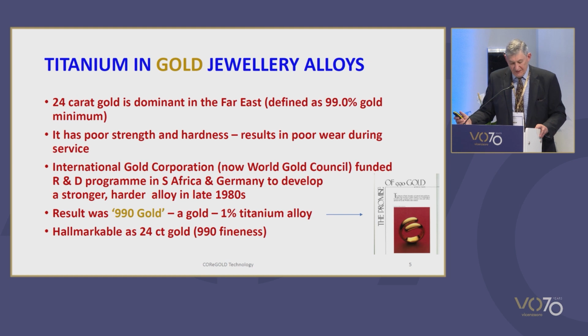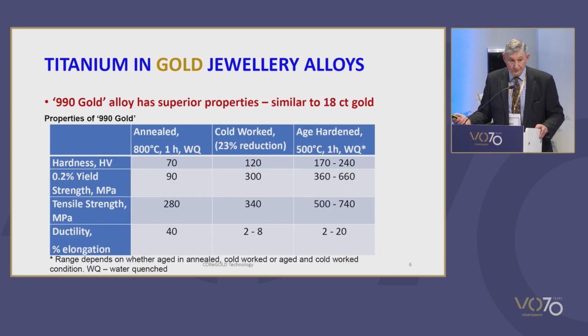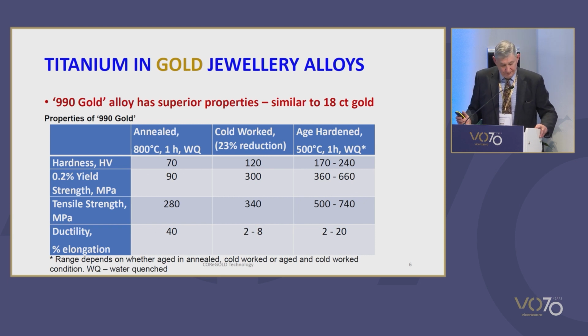This resulted in the development of 990 gold. It is a gold 1% titanium alloy. That is 990 fineness, so it is hallmarkable as 24 carat. It has mechanical properties considerably superior to 24 carat gold, approaching those of 18 carat golds, as we can see in the table. We can see that it has good hardness in the annealed, cold worked and age hardened conditions.